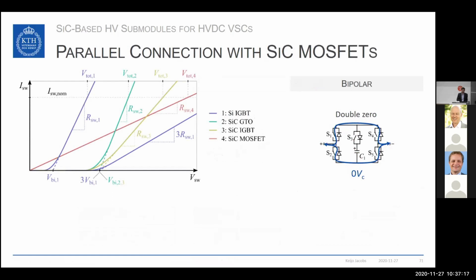Silicon carbide MOSFETs are specifically useful for such a parallel connection, and I will explain this on the example of the conduction characteristic. Here on the left side, you see qualitatively the conduction characteristic for different device technologies. For example, the silicon IGBT, the silicon carbide GTO, silicon carbide IGBT, and the silicon carbide MOSFETs. Interesting to see here is that the silicon IGBT has a built-in potential and then a resistive part. For the silicon carbide devices, which are bipolar, you also have a built-in potential, which is a bit higher, and then a resistive part. But for the silicon carbide MOSFETs, you can only see the resistive part.